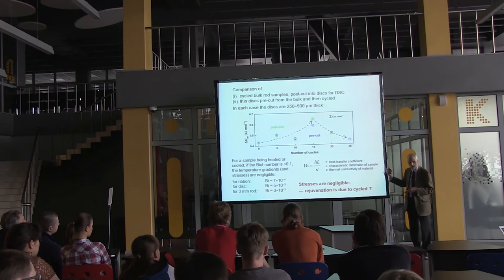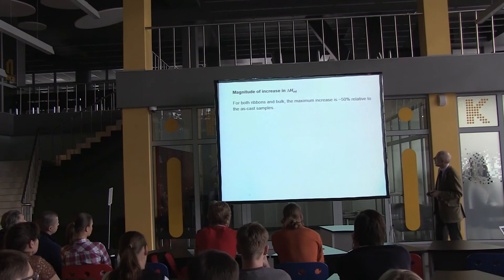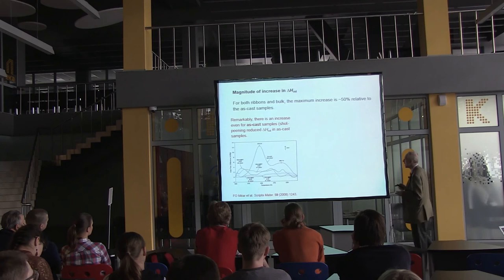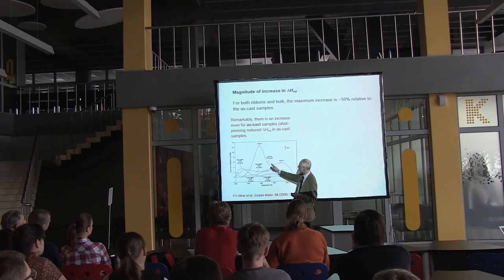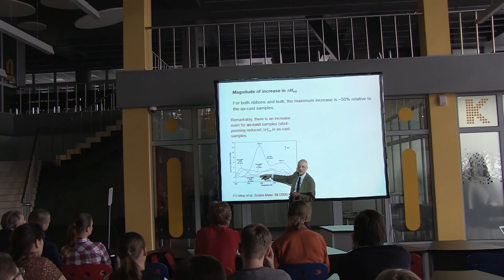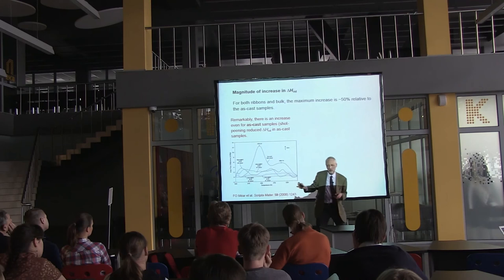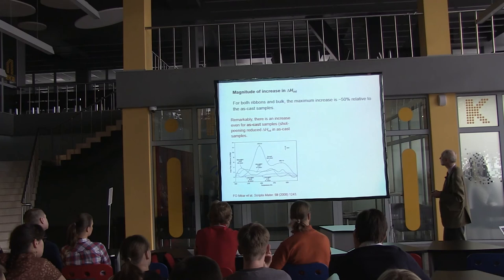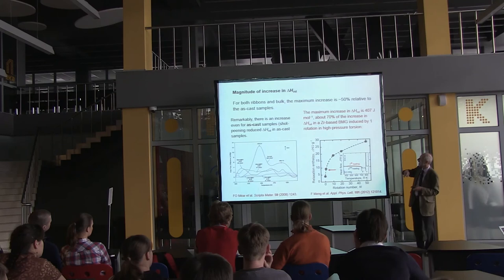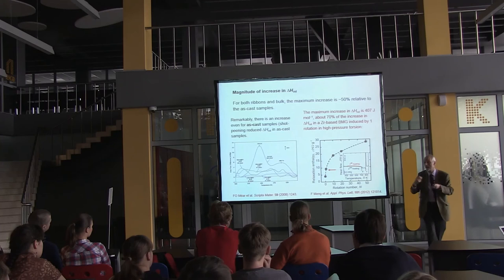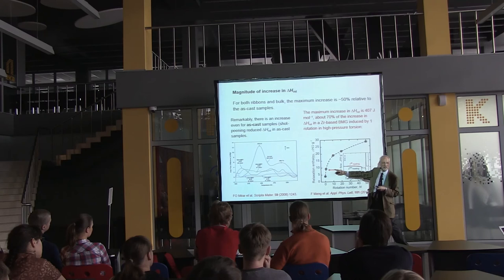The magnitude is about a 50% increase in stored energy. This is remarkable: recall the earlier work where mechanical deformation of an already-energetic glass actually reduced its energy. But this thermal cycling treatment increases the energy even beyond a high starting value — it is a more powerful treatment than mechanical deformation. And drawing Professor Valiev's attention to the numbers: the world record energy storage by high pressure torsion — heavy plastic deformation — stores a similar energy to just 10 thermal cycles to liquid nitrogen, which is like one turn of the high pressure torsion device.